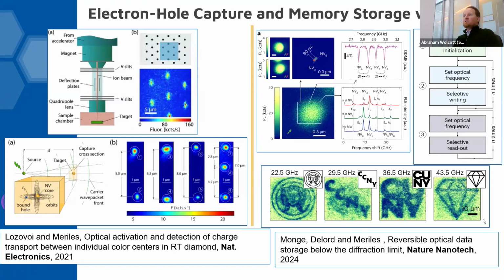So in a nice summary slide of the great advancements that are happening in the Meriles lab, on the left-hand side, you can see work with electron and hole transport and capture. You could have arrays of NVs, which are then illuminated, and you can control the NV minus, NV zero charge state, and then be able to capture the mobile electrons and mobile holes through the diamond lattice. The work on the left-hand side was done by Arthur, and he's now down in Princeton working with Natalie de Leon, and they discovered this massive cross-section for the capture of the electrons and the holes.